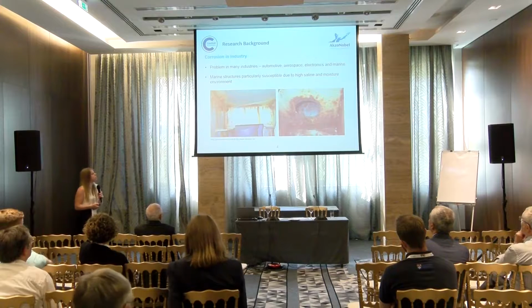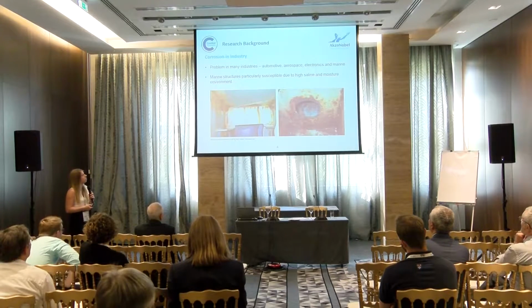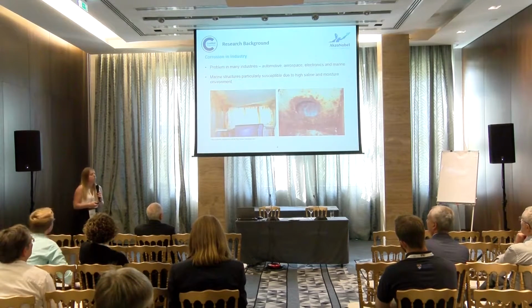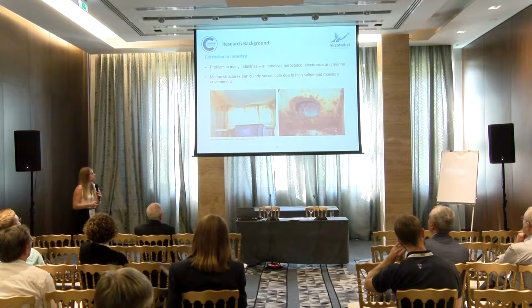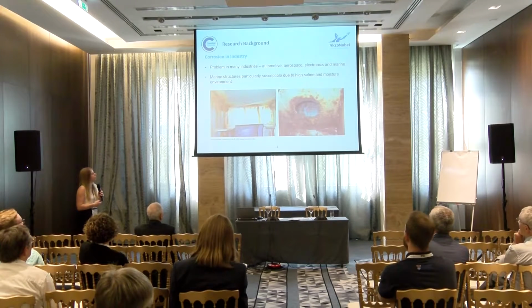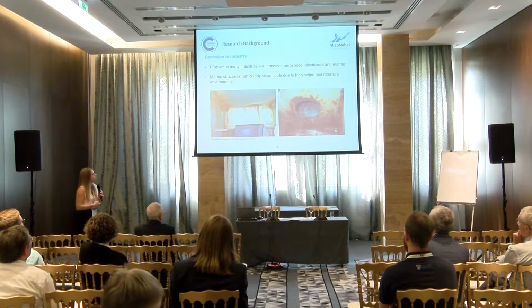This is just an image of a water ballast tank that has succumbed to severe corrosion. It has been observed in service that the worst cracking failure, and therefore corrosion, occurs within the corners and the welded areas of the stiffeners and around areas of complex geometry.